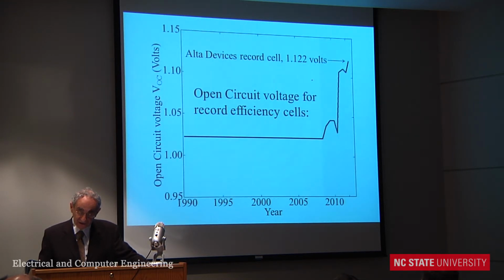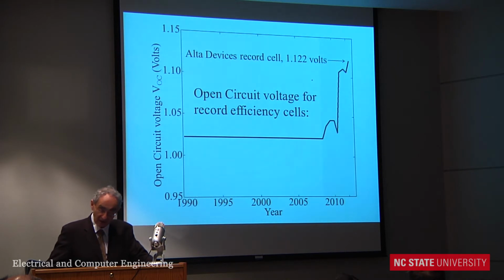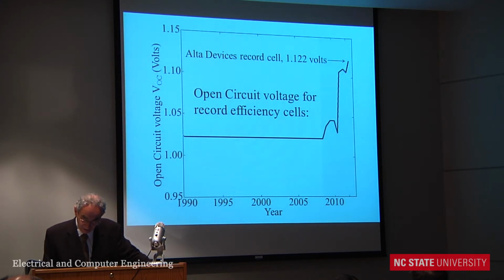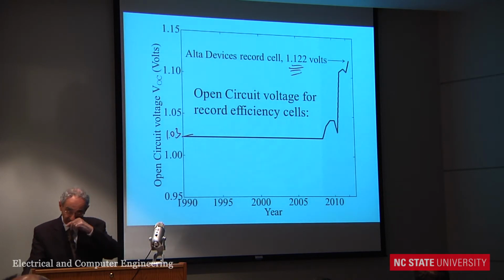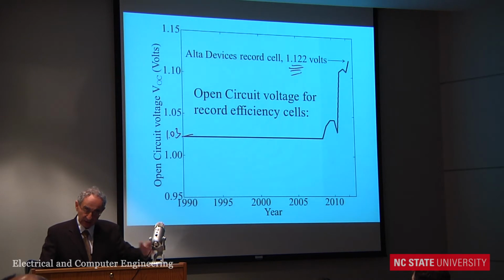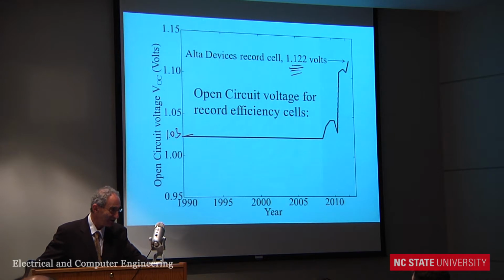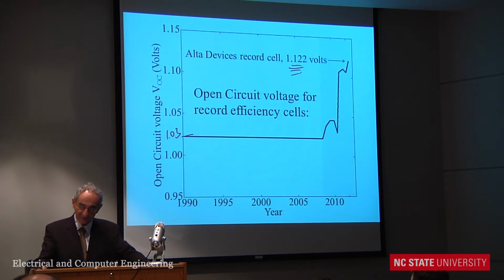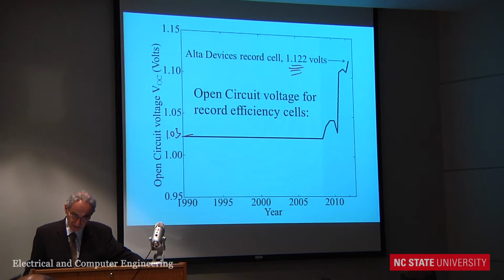Now, it was entirely due to a leap in voltage. So the previous record gallium arsenide cell was around 1.03, and the new record was 1.12. And that was rather surprising. In fact, at the company, I'm the co-founder of this company, they started getting big voltages, and I said, whoops, something interesting is happening. I've never seen a voltage like that. And then I told them how to go further, and this is the record voltage. So it's almost 1/10 of a volt, so it's a huge amount. That's responsible for the record.